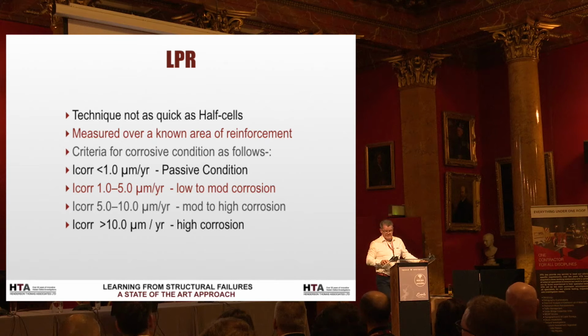So we would say it's better to try and do more testing to give you a far better idea of what's going on, because there have been major concrete repair jobs let when the concrete's been in a very, very good condition. And all you're doing is indicating the concrete's poor because it's damp. But if it's damp, there's no oxygen. No oxygen, no corrosion. And we've seen big areas of concrete removed to expose clean, non-corroding reinforcing steel. Clients don't really like that, to be perfectly honest.